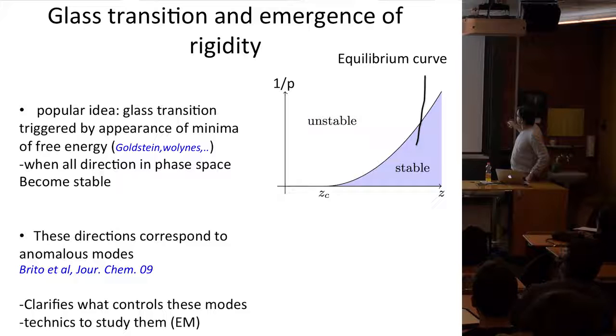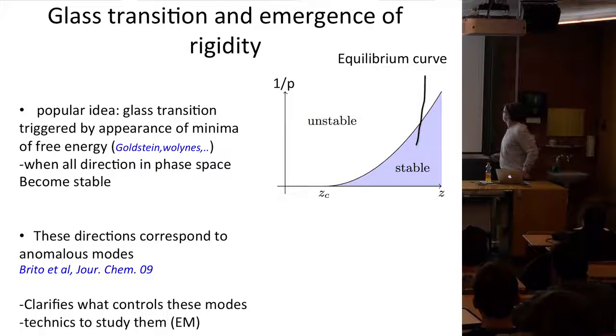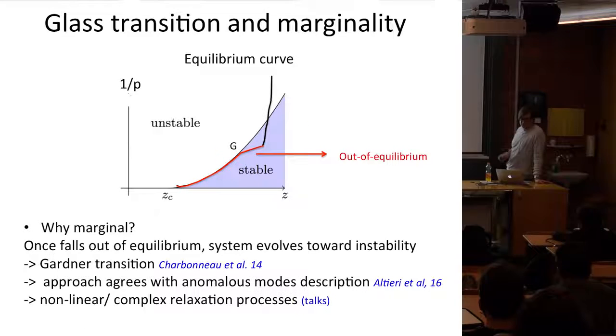And that the onset of the glass transition takes place when, so let's say you increase the density, so you increase the pressure. So in this phase diagram, you would be doing something like that. And the glass transition would take place in the vicinity of the point where you actually enter the stable phase. So you enter here, and then suddenly the dynamic changes. Instead of flowing along an unstable direction, it becomes activated. You can still penetrate in this regime, but the dynamic has qualitatively changed. So what I was telling you, this effective medium approach and so on, may give you a handle on what those objects are whose stability is actually exchanged.